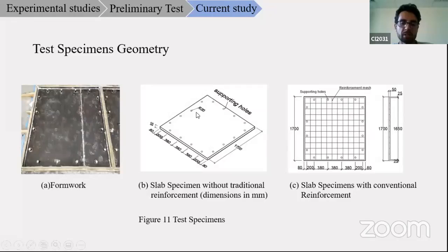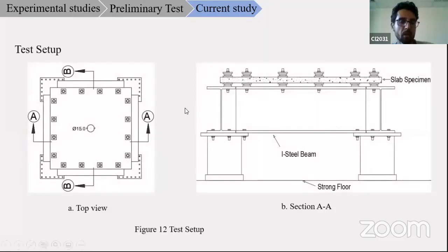The test geometry was adapted according to the trial studies. Here, just the supporting system was changed. Supporting holes were provided, and this hole was considered in the formwork. The slab specimen with the conventional reinforcement is shown here, and the reinforcement was in the form of mesh. So the test setup: a simply supported system was used. The simply supported system was provided with a spherical washer, and this can only rotate, but the horizontal movement was prevented.